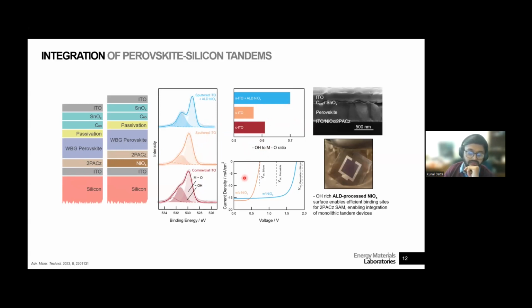And that led to a dramatic difference in the devices, because this is the IV curve of the tandem solar cell when we were not using the nickel oxide, and the VOC is basically the same as that of the silicon solar cell, and the JSC is similar to what you would expect out of a silicon solar cell being filtered optically by the perovskite solar cell. So it's as if the perovskite solar cell is not contributing anything to the device performance. But the moment you put the nickel oxide layer in between, it shoots up, right, and gets significantly closer to the sum of the VOCs of the perovskite and silicon solar cells. So that was very interesting for us, and that really made a big difference to how we proceeded.